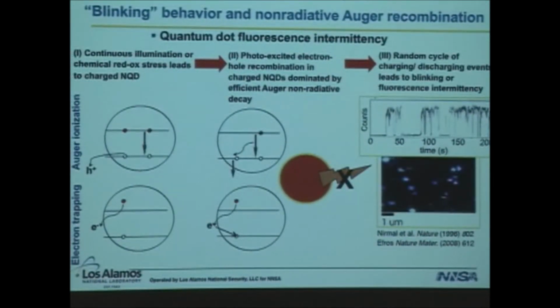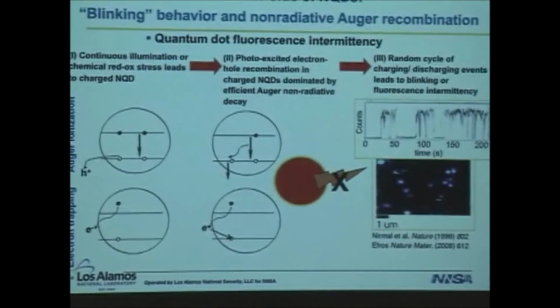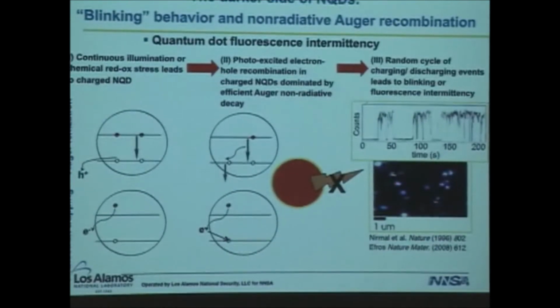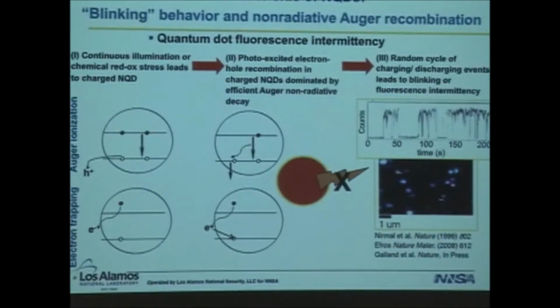But in this case, the quantum dot does not actually become charged, and even though the quantum dot becomes dark, its lifetime does not change, in contrast with the quantum dots up here. But anyway, this will be coming out shortly. It's in press in Nature, and so it's giving us a better understanding of what's going on with blinking, towards the hope of creating more and more types of quantum dots that do not exhibit blinking.